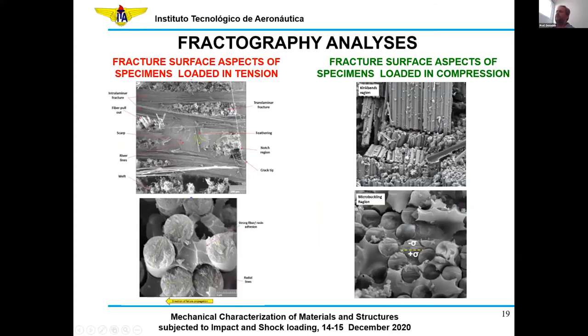We also performed some fractography analysis to understand how the composite fails here and which sort of stresses are dominant in each failure process, either in tension or in compression. We could see, as expected, that microbuckling was a predominant failure mode in compression, and tensile failure in the fibers was a dominant failure mode in tension.